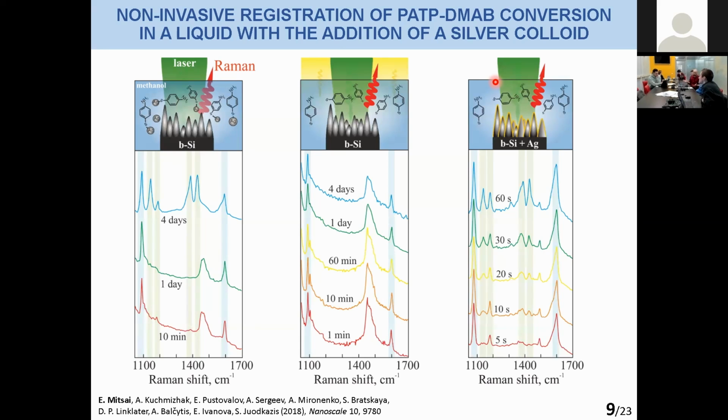So it's all right in the sense of the formal side of what you defend. Yeah, but the question is, of course, it's probably two factors. But then I wonder, if you change the concentration of the analyte, this obviously affects the rate of chemical reactions because we have the Arrhenius law. So you do the experiment with another concentration of the analyte, you grab this data, and by comparing two sets of data, it's just a guess, you might discriminate these two reasons for changing the Raman signal. So this is potentially possible.